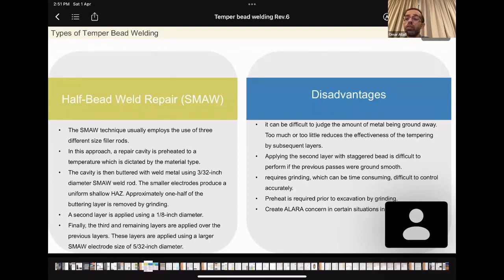So the disadvantages of this technique is that it is quite difficult to judge the amount of metal being ground away. So this is one of the most critical parameters. So why is temper bead welding not preferred by many owners? Because it depends on the competency of the welder. So removing half of the bead and controlling the overlap may seem easy, but it's quite difficult. Too much or too little reduces the tempering effect of the subsequent layer.